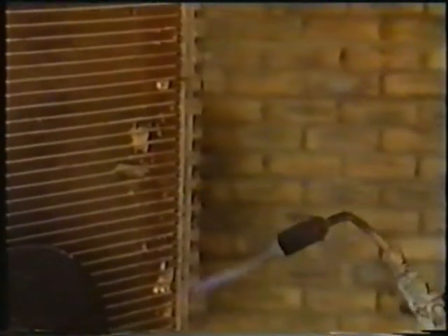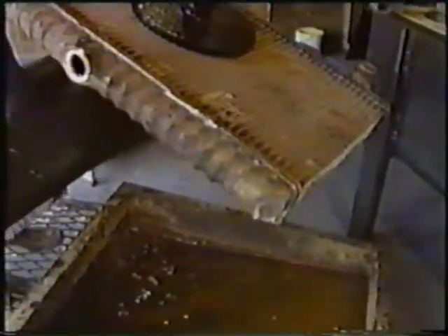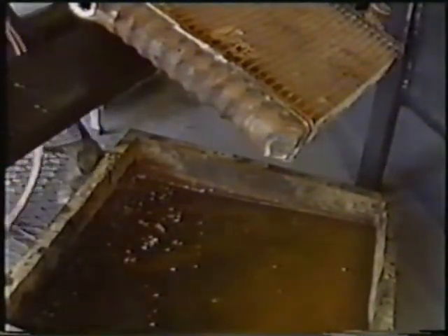This ensures that solder drops to the bottom and any flakes of paint or dirt float to the top, so that at the end of each day you can scrape off the dirt and you have a good clean solder dross. Also notice that there is no need to use a big torch flame. A nice pencil-like flame, giving a hot concentrated flame, will quickly melt off the old tanks and side frames.